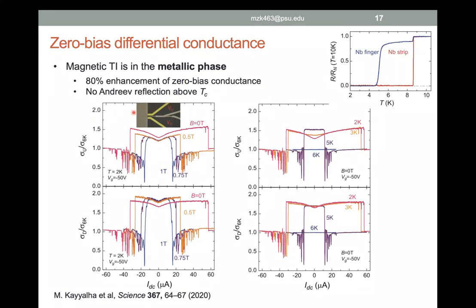And another sanity check, to make sure these are actually Andreev reflection, is if you increase the temperature of the niobium above the niobium critical temperature, then you see a flat line. So no enhancement in the conductance is observed for these samples above the critical temperature of the niobium finger. So that indicates that whatever we are seeing here is caused by the superconducting state in the niobium finger.